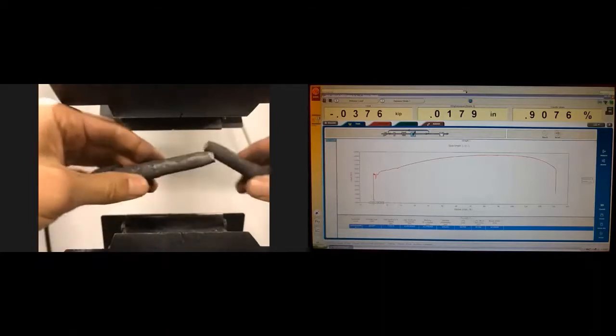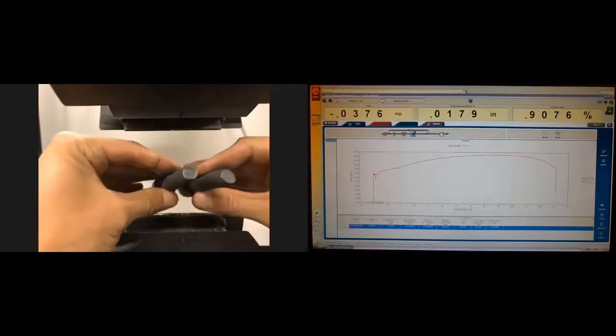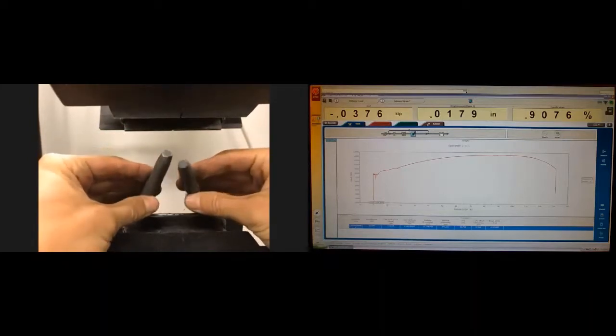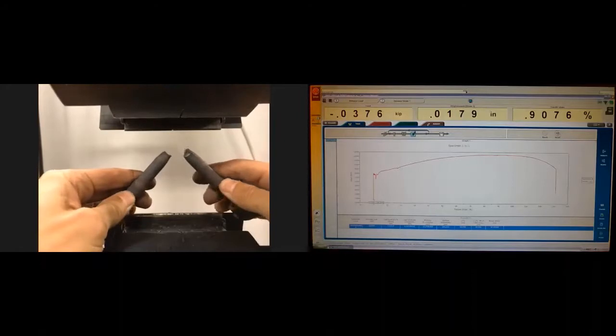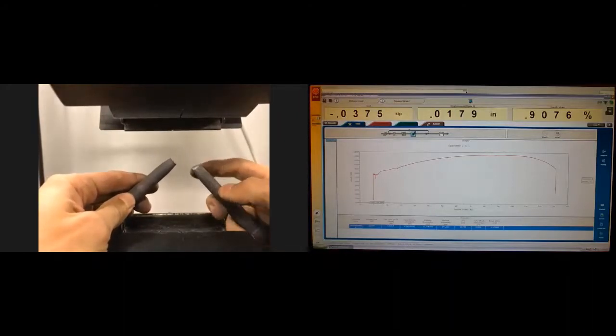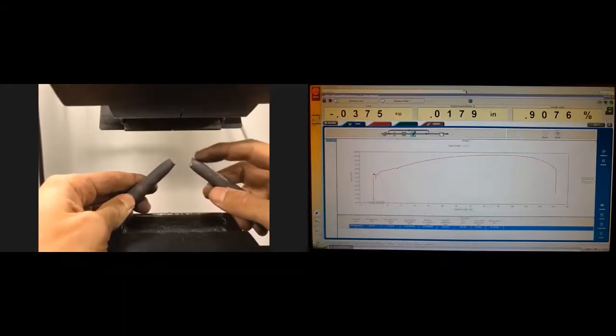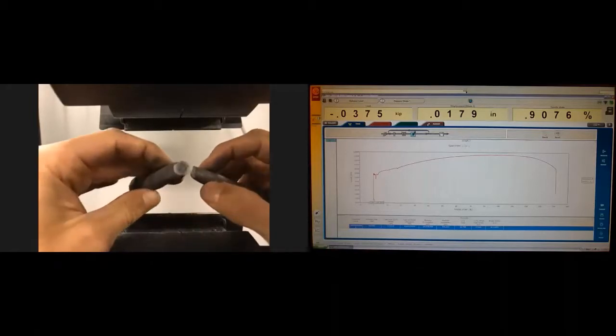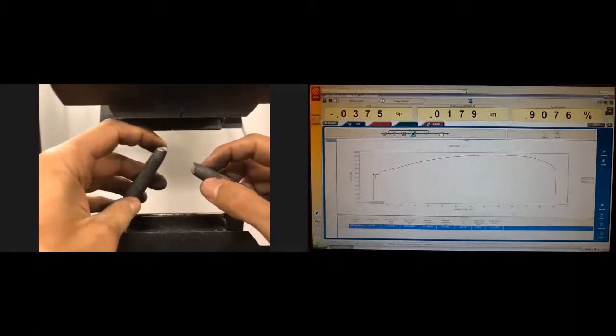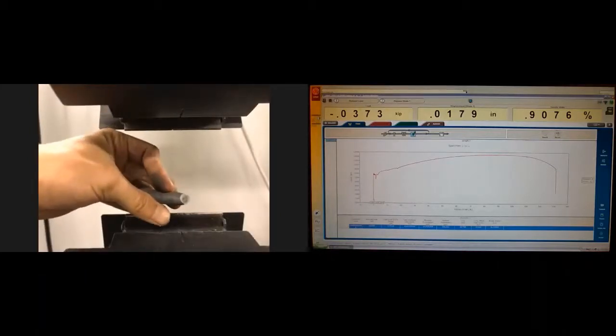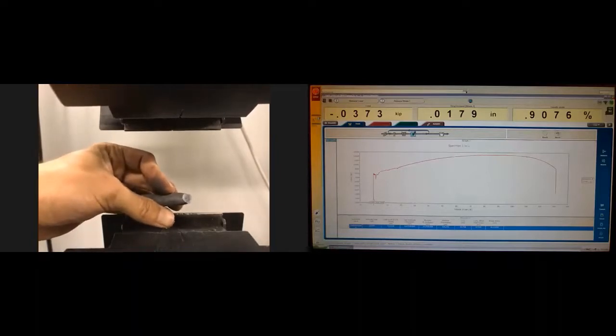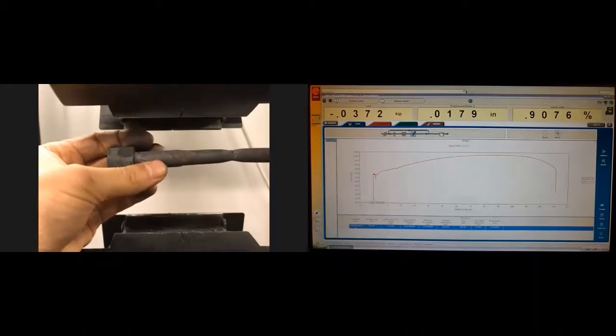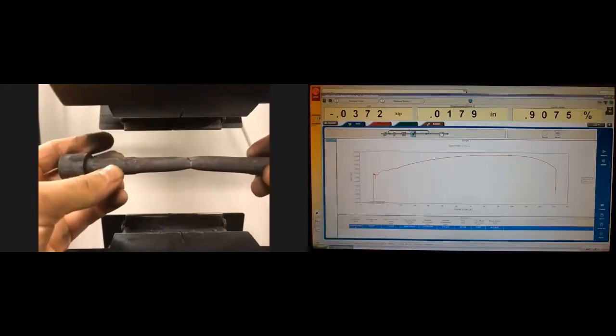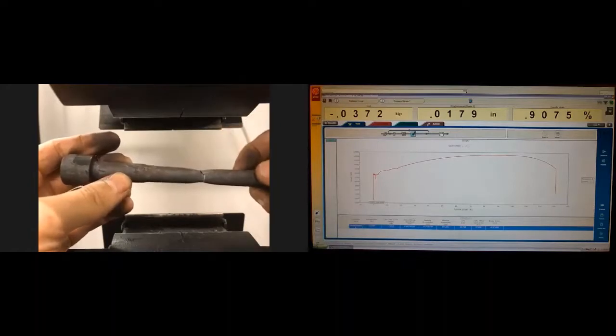And when you look at this sample like this, you may see that there is a cup and cone type of geometry. So it is shearing of the sample at the surface level and more triaxial, more complicated stress condition right in the middle of the sample, more kind of brittle behavior due to triaxiality of the stress state. There is substantial plastic deformation right above the necking region, so this is the weakest point.